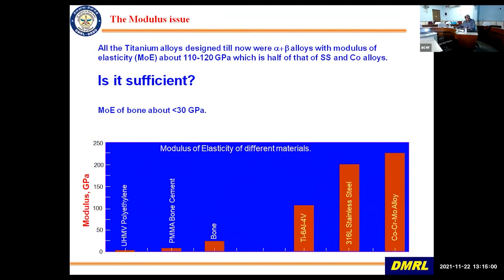So as you can see, for the different materials, the elastic modulus is plotted. Co-Cr-Mo alloy. These are all biomedical alloys which are there. 316 stainless steel. Bone is here, and this is PMMA bone material. UHMW polyethylene, which is again used for biomedical application. And so new titanium alloys have got much lower modulus and thereby much more compatible with bone structure. And this is another newer titanium alloy, Ti-35Nb. So this is completely a beta alloy, as you can see, and although we would still like to go this side, still lower, there are studies which are on. But it is much lower as compared to other biomedical material which we had earlier.